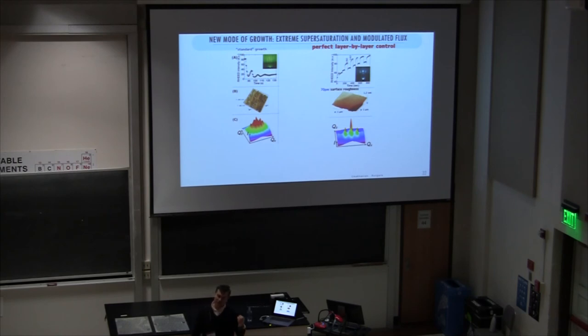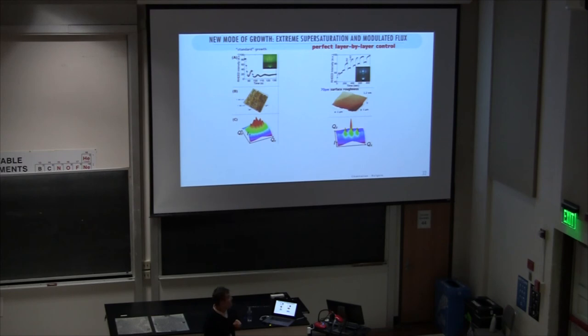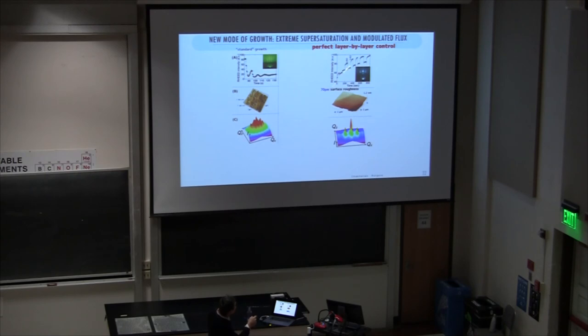I highly encourage everyone to invest time in a new mode of growth we discovered called interrupted growth: grow as fast as you possibly can. This is contrary to conventional understanding. We grow the same material at absolutely the same pressure and temperature, only changing how fast material is delivered to the surface. Delivering as fast as our laser allows, you can see the intensity actually increases beyond the starting substrate level — meaning the film is better than the single crystal surface we started on. Result: 70-picometer roughness, beautiful films.